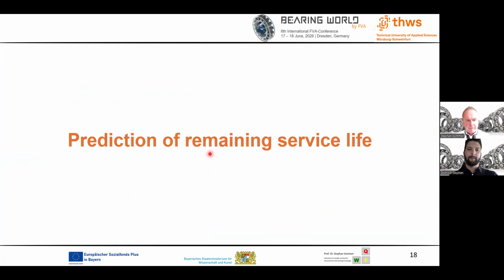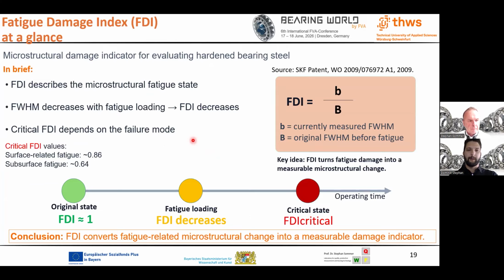Now we move from measurement comparison to the concept of fatigue assessment. The Fatigue Damage Index, or FDI, is a microstructural damage indication for hardened bearing steel. It is based on the ratio between the current measured FWHM value and the original FWHM value before fatigue. In the unloaded condition, the FDI is close to 1. Under fatigue loading, the FWHM decreases, and therefore the FDI also decreases.